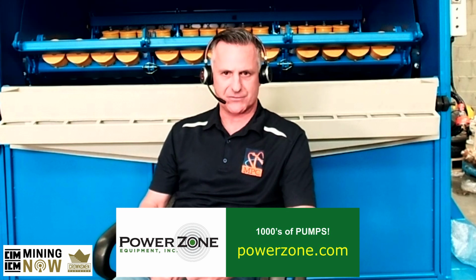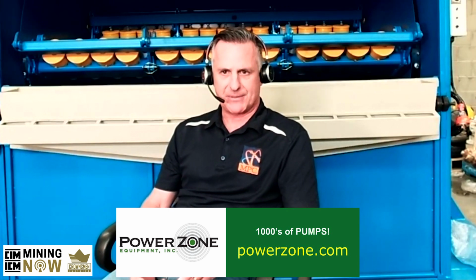The difference between the bottle roller and the PAL behind you is the pulverizing aspect of it. If you're to do the bottle roll technique, and you're taking ore from the pad before it goes into the crushing circuit, you're taking quite large pieces of dirt or rock. You then have to sample prep it, which means splitting it down from larger weights to smaller weights, crushing it, and then grinding it in a pulverizer, which may be a ring pulverizer, a piece of laboratory equipment which will take it down to micron sizes, say 50 micron, 60 micron, 70 micron.